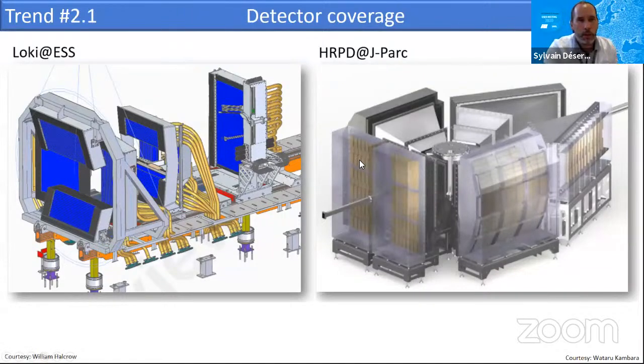Now I will also speak about new trends, 3-4 slides about detectors, and I will begin with detector coverage. On the left side, you can see the LOKI instrument, which is a SANS instrument. Scattered neutrons will come from the left. You can see there are 3 detectors that will work simultaneously to collect at the same time the largest angles here, and the smallest angles will go through the whole detectors here, and they will be collected on the last detector. So the idea is really to be able to measure the full Q range in one shot and get a dynamic range in Q of the order of 3 orders of magnitude.